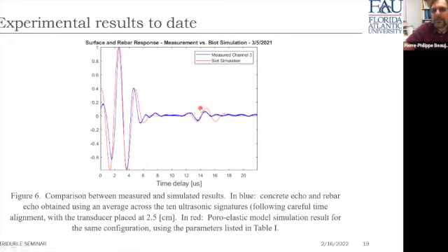So in this last plot in figure 6, what I'm showing is a comparison between measured and simulated results. In blue, it's going to be the concrete and rebar echo obtained using the average across the 10 ultrasonic signatures. And in red, we are going to see the Poro-Elastic model simulation result for the same configuration using the parameters listed in table 1.